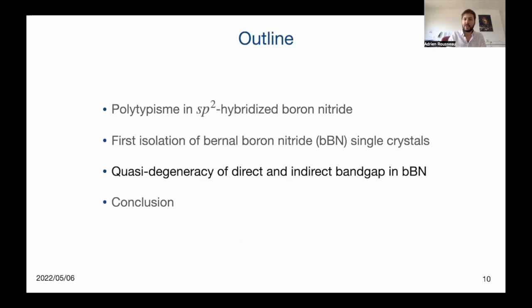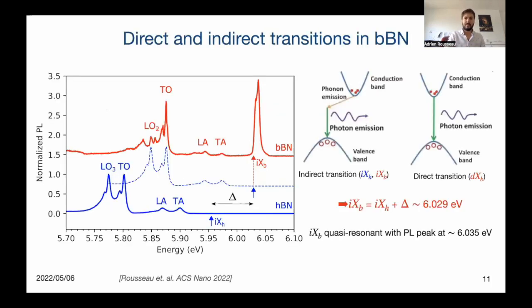Now we'll discuss the quasi-degeneracy nature of the direct and indirect band gap in Bernal boron nitride. By measuring the typical photoluminescence spectrum on Bernal boron nitride, as represented in red on the left, we observe again the strong photoluminescence peak at 6.035 electron volt, which we attributed to the direct transition in Bernal boron nitride. Below 6 electron volt, we also observe a series of lines.